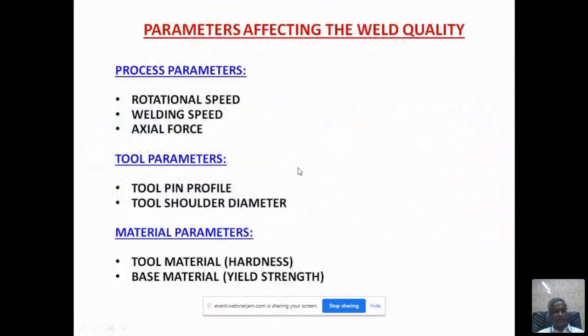Right. So the friction welding process now, as on date, is a very good process. The best process, I can say, for joining aluminum alloys, magnesium alloys, copper-based alloys, because there is a boundary: a melting point less than 1000 degrees centigrade. If the melting point of the material is less than 1000 degrees centigrade, friction welding is the best process. But above 1000 degrees, it has potential, but the main problem is tool material. The tool material is the big challenge here.